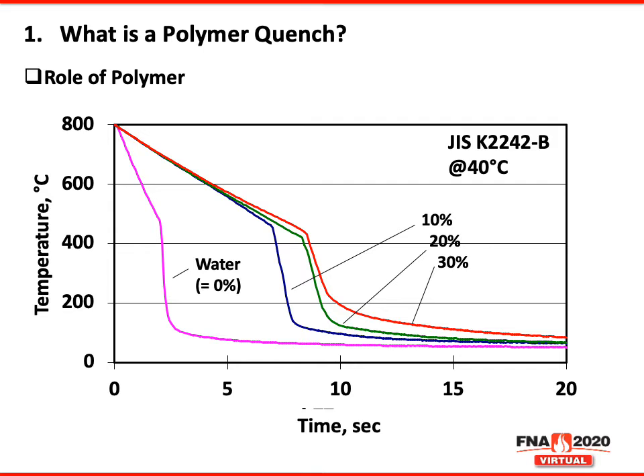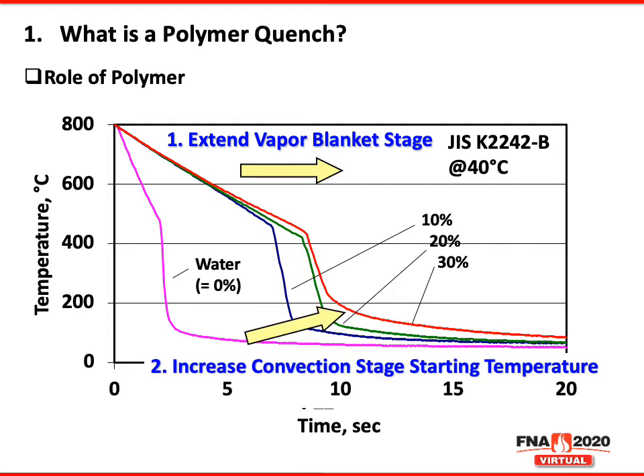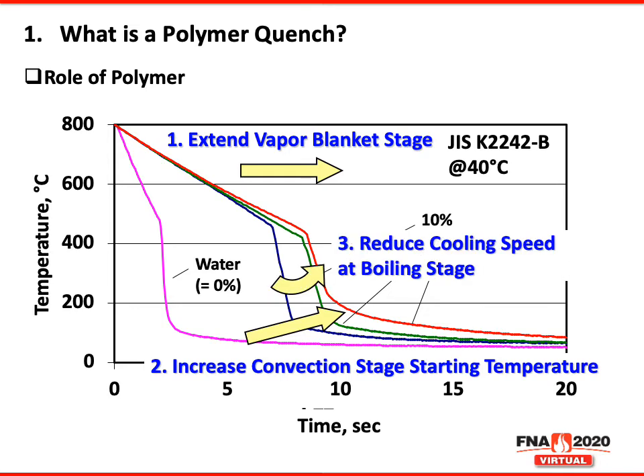So the role of a polymer here, you can see, is we have water here, and then these are different concentrations. The higher the concentration, the further to the right the line moves, and the slower the quench speed actually is. You can see it extends the vapor blanket stage and increases the convection stage starting temperature. And it reduces the cooling speed at the boiling temperature.